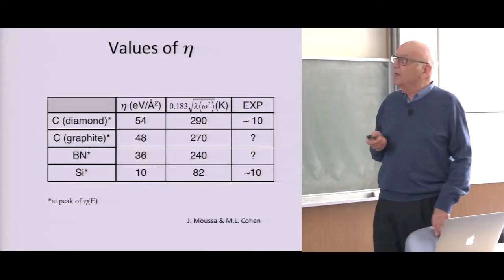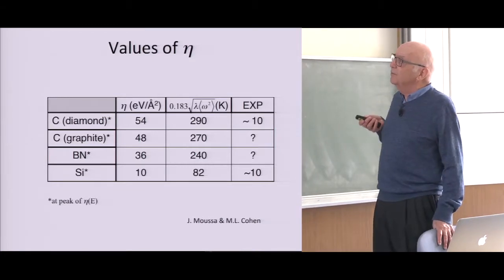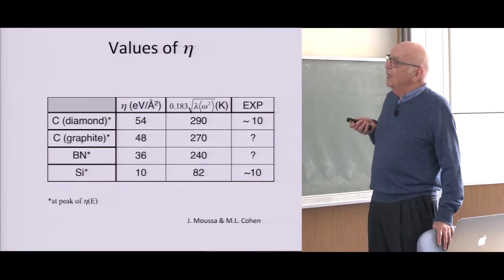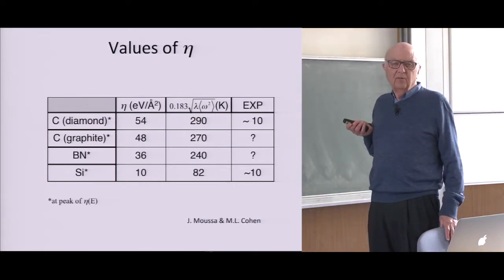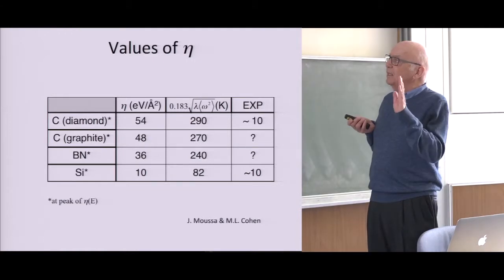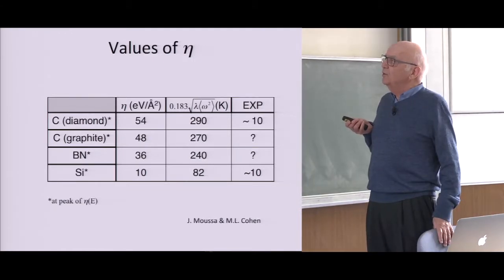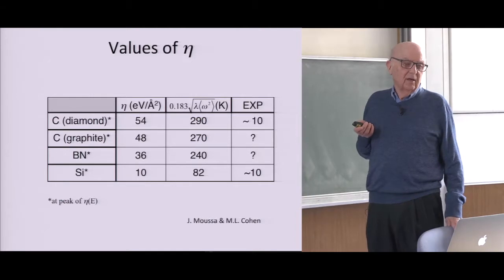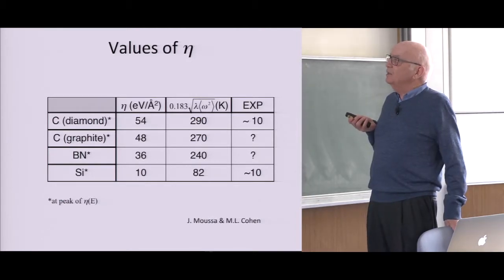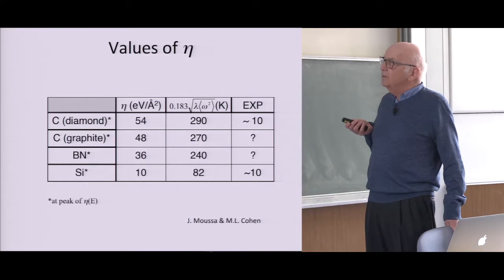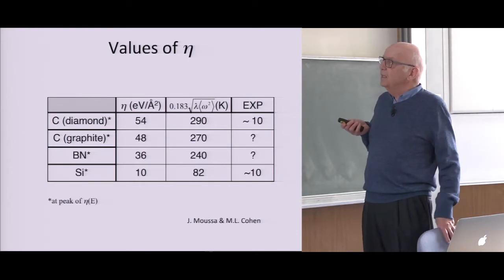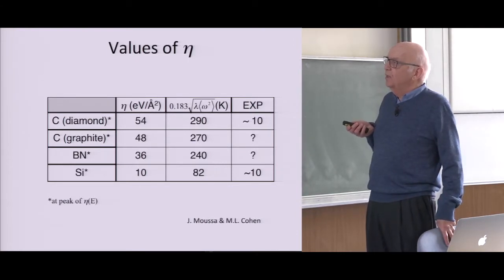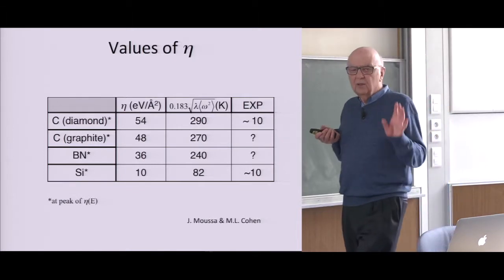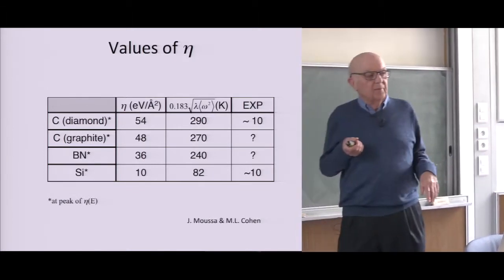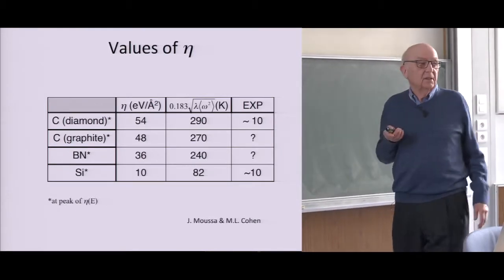So where is the theory on this? Well, when we worked on it, we got for a diamond, if you could get the density of states, if you can get enough boron in and get the peak at the proper place, you could get 290 Kelvin. At the time, it was 10 degrees. Graphite is a little trickier, but is also in that range. And boron nitride and silicon, using that formula, if you can dope, this is where you get.